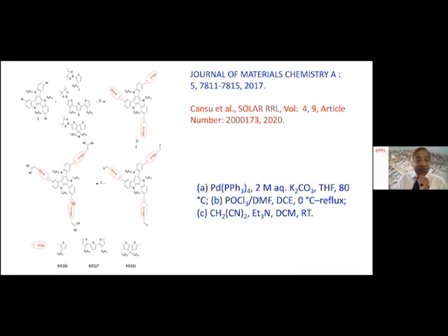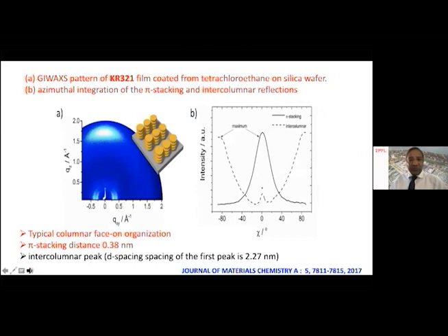If you look at KR388, it has one thiophene, and another molecule, KR321, has three, and KR383 has two thiophene groups in the bridge. But the core is the same, a flat core. So the take-home message: we have a flat core and thiophenes as a substitution to interact with the perovskite composition. That's the logic behind this. Since we have a flat core, like phthalocyanines, they assemble one on top of the other, forming a columnar structure. And this columnar structure induces the charge extraction from the perovskite through this column. Therefore, we can use this type of material without any dopants.